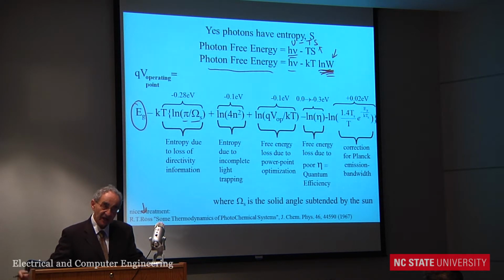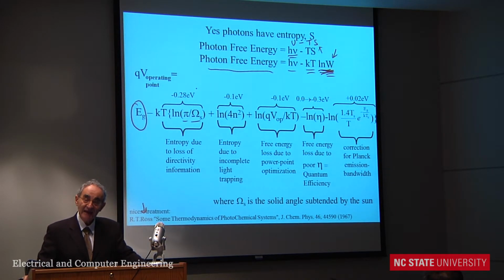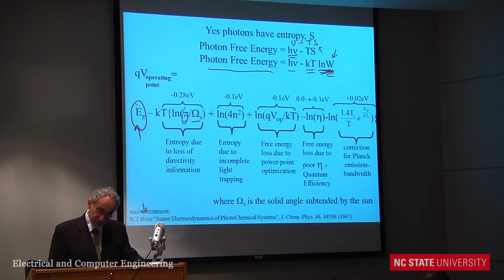Natural log of 30,000 is about 12, and then 12 kT is about 3/10 of a volt, and that is the biggest entropy term, and that is the biggest drop in voltage. You never get the band gap. You immediately give up roughly 3/10 of a volt due to the solid angle subtended by the sun.